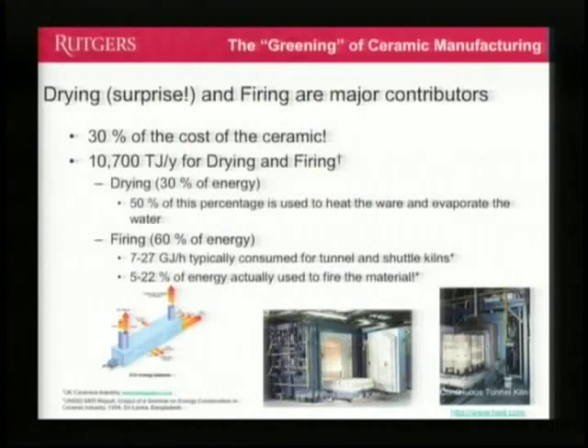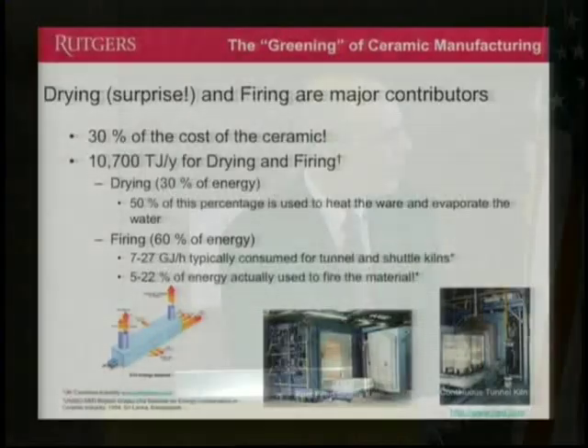So here's the surprise. It's drying and firing that contribute a lot of the energy consumption. Roughly 30% of the cost of a ceramic is put into the energy for drying and firing. 30% of that energy that I'm mentioning here is spent drying, and it only takes double that for firing. And that's the reason why. Even though drying is a low-temperature process, the length of time required in drying is so much longer than a firing step that your energy consumption can in fact be comparable.